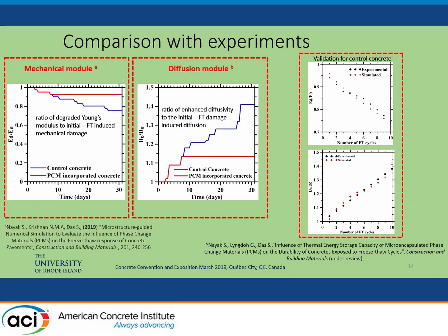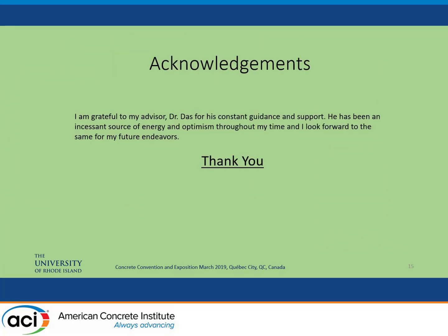To quantify these two modules: in the mechanical module, we track time versus the ratio of degraded Young's modulus to initial Young's modulus as a measure of induced mechanical damage from freeze-thaw cycles — control concrete degrades more than PCM-incorporated concrete. For diffusion, the ratio of enhanced composite diffusivity to initial diffusivity shows control concrete with higher diffusivity, implying lesser durability. These results are validated against other experimental research and match closely with our simulations. I'm grateful to my professor Dr. Das for his guidance and support. Thank you.